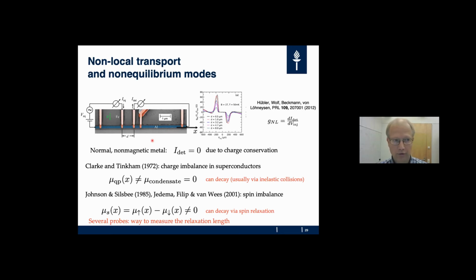If this aluminum is in the normal state, and if the injectors would be non-magnetic, then the detector current would be simply zero due to charge conservation. However, Clark and Tinkham showed in the 1970s that if you take the metal to the superconducting state, such an experiment can probe a charge imbalance in superconductors.